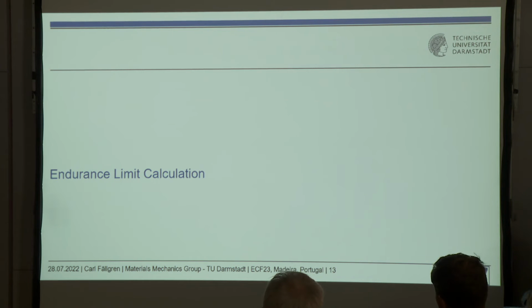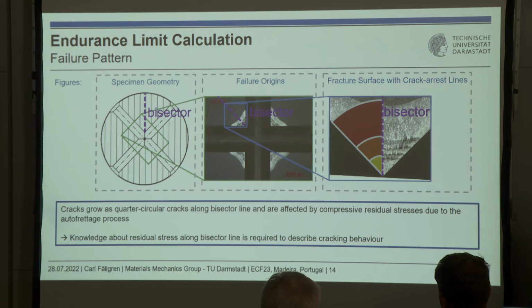So now, endurance limit calculation. First of all, what does it look like when those specimens fail? Here on the left side you see a cut through the specimen geometry with those two intersecting bores at a 90-degree angle. And the failure originates, as I told you, from the notch intersections. So we have 4 cracks which are growing, and those cracks grow as quarter circular cracks. Now you see this kind of butterfly shape. I will get to that exactly.